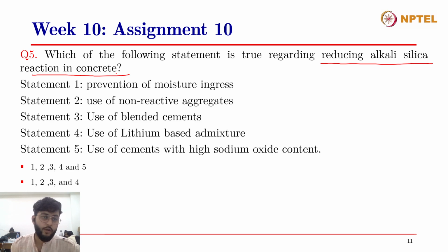All right, let's discuss all these statements one by one. Before going there, what is alkali silica reaction? Essentially, when there are reactive aggregates present inside the concrete, and by reactive aggregates, I mean that the silica source in the aggregate is amorphous in nature. It is reactive silica, and therefore, as we know that the pH inside the concrete is alkaline, the pore solution of the concrete consists of different alkalis like sodium ions or potassium ions. So these alkalis get inside the reactive silica aggregates.